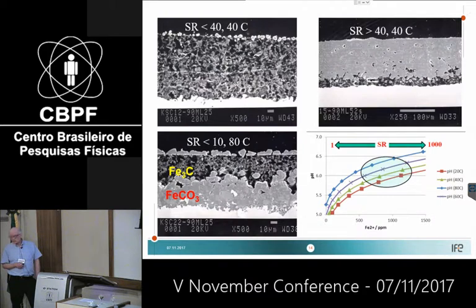And if you have too little supersaturation, you will not form a dense corrosion product film on the steel. This is a cross-section of a steel studied in a microscope, so this is 10 micron. So you just get a porous structure, no protection. And then you increase the supersaturation, and you start to precipitate iron carbonate. But in this case, it's too low. You precipitate in this porous film, but not close to the metal, where you actually need the protection. But in this case, the temperature is increased, and that changed the precipitation. And here you got iron carbonate close to the steel after some time, and you got protection.